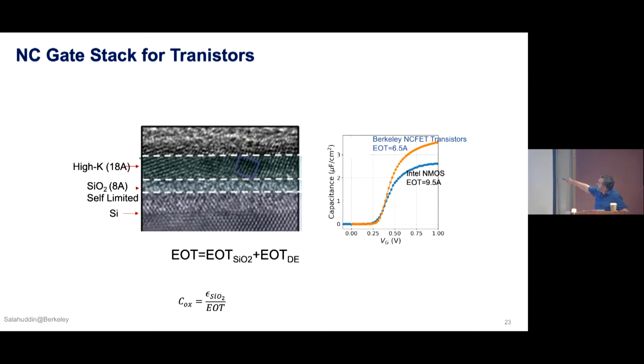Here I'm showing data from a publication for an Intel NMOS transistor where EOT is around 9.5 angstrom. But for the same kind of structure with similar thickness, what we get here is 6.5 angstrom. So you really cannot get it just using this, unless you think that the EOT of this gate stack is adding a negative contribution.